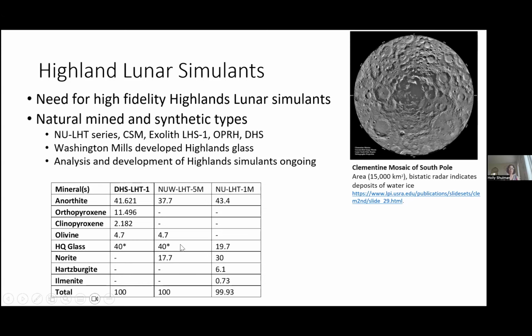And HQ for high quality, which is not a thing that ceramic and glass scientists use, but apparently for NASA, this means that it's highly amorphous, so it's non-crystalline. So glass is not really purely amorphous. It actually has short range order, but by X-ray diffraction it appears totally amorphous. And Doug Rickman used norite in that mix, but by using these pyroxenes, we're able to get the exact same chemistry here. And pyroxene is actually close, it's what we're dealing with in Highlands regolith.